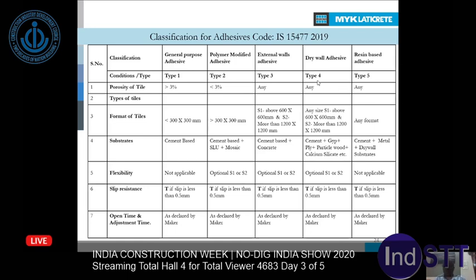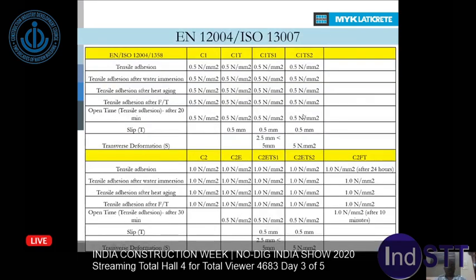Similarly, if it's a drywall adhesive, we recommend type 4. If it is an area where you want to fix metals or bond metals, then we recommend epoxy or resin-based adhesives. And similarly, EN, of course, the Indian standards are also a combination of EN and American standards. They have classifications. C1 is a very basic, unmodified adhesive, and T comes with slip resistance. S1 means it's more highly deformable or flexible. S2 even more than that. And C2 is highly modified.